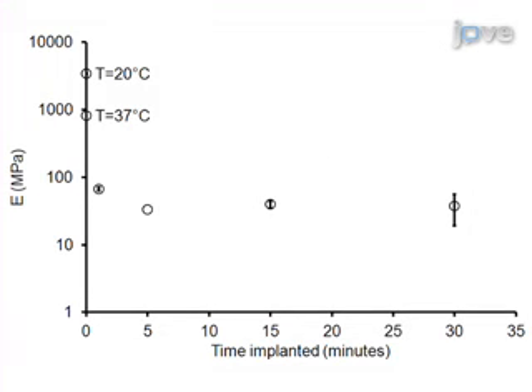In this final plot is the Young's modulus versus implant duration for the samples placed in the cortex. After about 5 minutes of implantation, the sample displays little change in the Young's modulus. This suggests that the sample reaches saturation and minimum stiffness within this period of time.